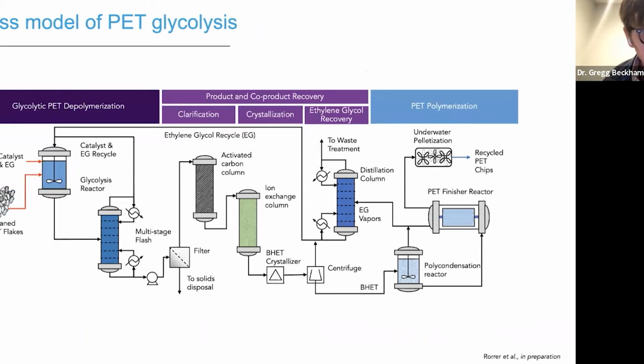What about this process at scale? Like I showed you for the enzymatic PET hydrolysis, we've also built a process model in Aspen and built a techno-economic analysis and life cycle assessment of PET glycolysis. Again, this is what I showed you earlier, now drawn out in a little more detail. You have a catalyst and ethylene glycol, you clean PET flake, you run the reaction. This goes through a flash, and so you can recover your catalyst and some of the ethylene glycol. This goes through a filter to remove solids, activated carbon to remove junk, dyes and pigments and all kinds of other things. It goes through ion exchange to remove any metals, and then it goes through a BHET crystallization step and a centrifuge. You have BHET, which you can then repolymerize into PET, and then you can make recycled PET chips.